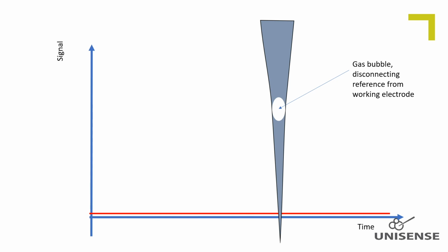There must be an air/gas phase in the electrolyte cavity in order to make room for temperature-induced expansion of the electrolyte. And if the sensor package was turned upside down during shipment, a gas bubble can be trapped in the tip. Such gas bubble can be removed by shaking the sensor like it is demonstrated here. The bubble will become loose and rise to the top of the electrolyte cavity, and connection will be restored.